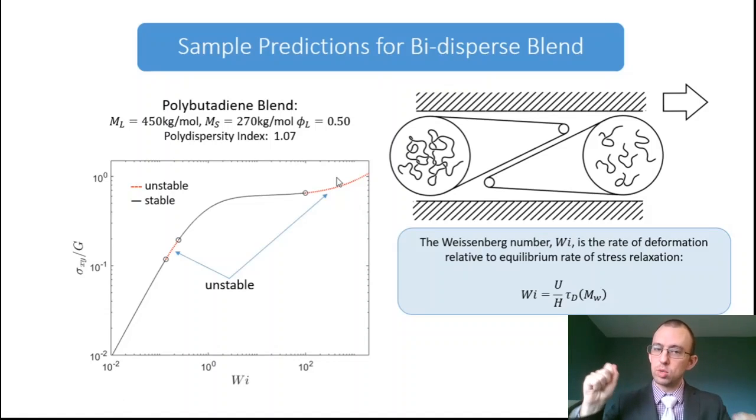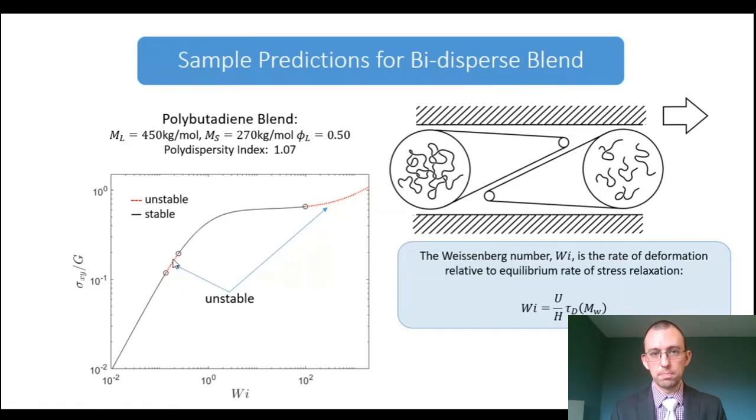You've exceeded the stretch relaxation time with the deformation rate. And so those long chains start to stretch, and then they once again have the stronger driving force to move towards lower shear rates, hence driving instability again. Okay, so with this established, let's look at the nonlinear dynamics of a shear-induced demixing instability that occurs within this low shear rate window here.